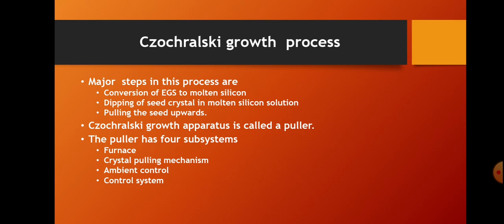The second step is dipping a seed crystal, which has the same characteristics as the single crystal silicon we want to grow, into the molten silicon in the crucible. The molten silicon will attach to that seed crystal. The third step is pulling the seed crystal upwards so that the molten silicon attached to it will solidify, giving us a silicon ingot. That is the overview of the three steps.